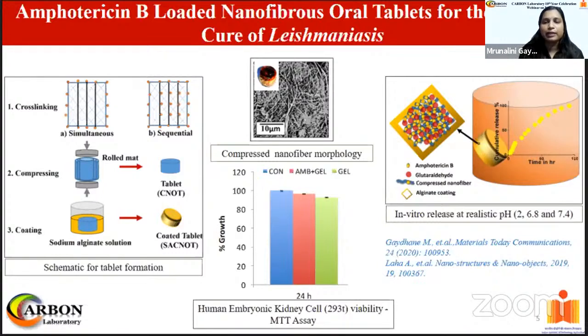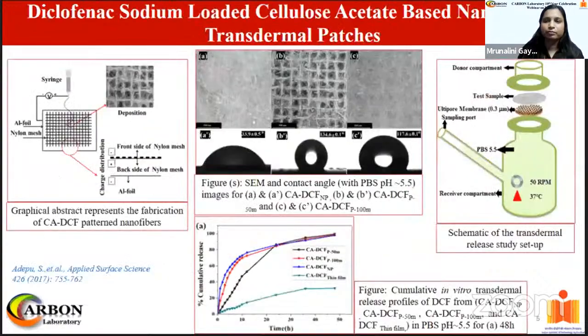When the release study was carried out in realistic pH conditions, mimicking the physiological conditions of the stomach, intestines, and duodenum, we found a zero order profile with 100% drug release achieved by 96 hours. Further, these oral tablets of amphotericin B were found to be non-toxic to kidney cells due to slow and sustained release of amphotericin B. In case of oral tablets, the release rate was found to be dependent on the degree of cross-linking of nanofibers, the compression pressure, and the thickness of alginate coating.